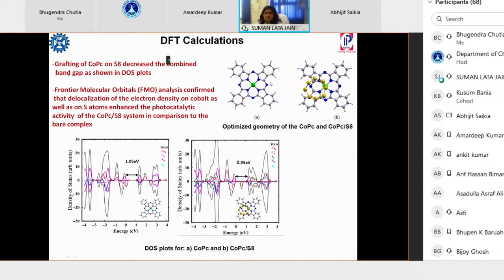We performed some DFT studies to understand the mechanism. Although these studies are in progress, we are working in collaboration with Dr. Shelja at CSIR NCL. Some of the DFT studies showed that connection of octasulfur with the cobalt increases the reactivity in comparison to the cobalt complex alone, because the attachment of the cobalt phthalocyanine with this octasulfur increases the electron mobility or electron density on the catalyst overall. So the electron availability to react with the carbon dioxide increases. That is one of the possible reasons for the increased reactivity of this hybrid system rather than the bare complex.